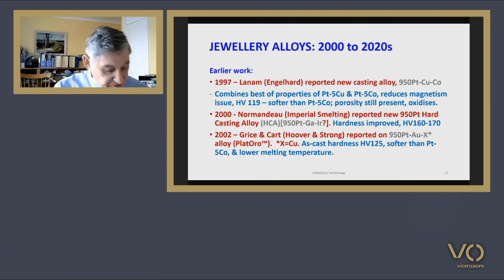Another alloy development was presented by Normandeau in 2000, in which he reported on a new 950 platinum hard casting alloy with an as-cast hardness of 160 to 170 Vickers, which is much higher than the platinum 5% cobalt alloy. Little detail is given on the composition, but the discussion in the paper points to it being a 950 platinum gallium iridium alloy.